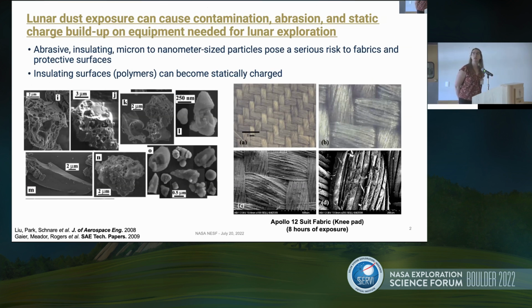In particular, we're worried about the abrasive, insulating, and size aspects of these particles. So in the lower left-hand images, you can see an example of particles returned from the Apollo missions. And then in the right-hand images, you can see the abrasive wear that occurred on Apollo suits during the very short durations of EVAs, which are obviously much shorter than what we expect during Artemis missions.